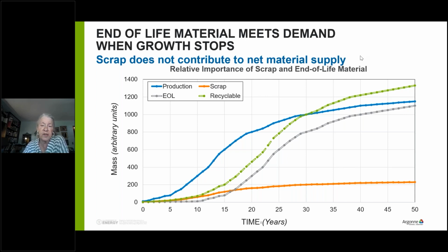The orange curve is the other interesting one, and that's scrap. We've arbitrarily assumed in this that 20% scrap is made during the production process. And that scrap does not add to the supply of material. In fact, it's material that needs to be processed multiple times. But what you can see on the green curve is the sum of the scrap plus the recycled material. And that is the quantity of material that is available for recycling.